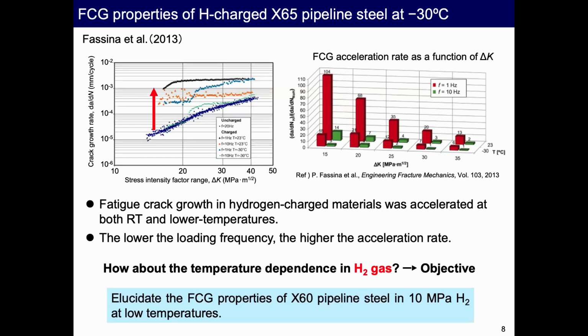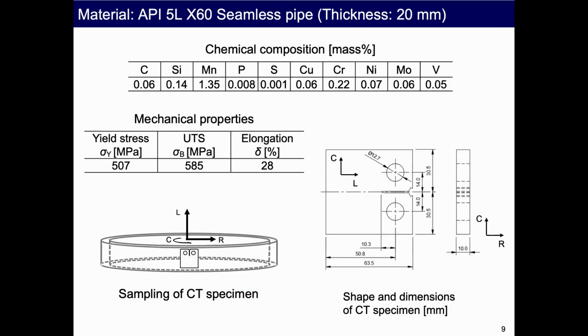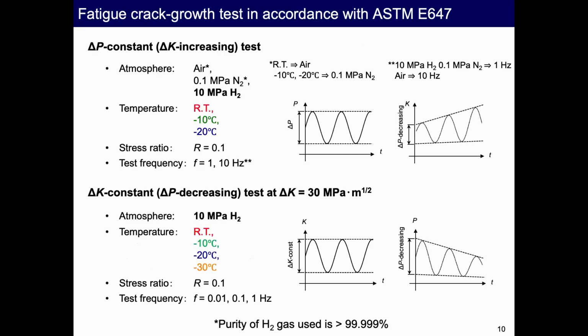So the objective of this study is, the question is: how about the temperature dependence of fatigue crack growth properties of X60 pipeline steel in 10 megapascal hydrogen gas? We prepared this X60 seamless pipe, as shown here, and we made a fatigue crack growth specimen. This is the shape and dimension. And we performed two types of fatigue crack growth testing in accordance with ASTM standard.